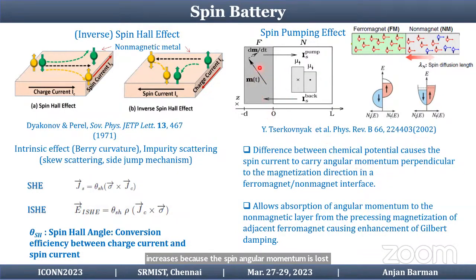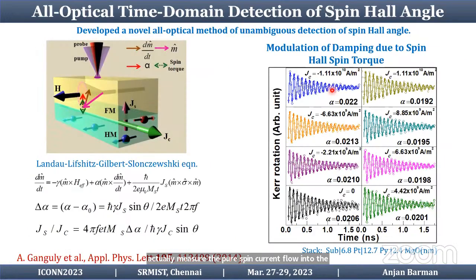So from the modulation of damping, you can measure the pure spin current flow into the non-magnet and various other properties. So we developed a novel all optical modulation method for unambiguous detection of the spin Hall angle, where we used the modulation of damping due to spin Hall torque, spin torque. Here we have taken a ferromagnet, and adjacent to it we have deposited a heavy metal.